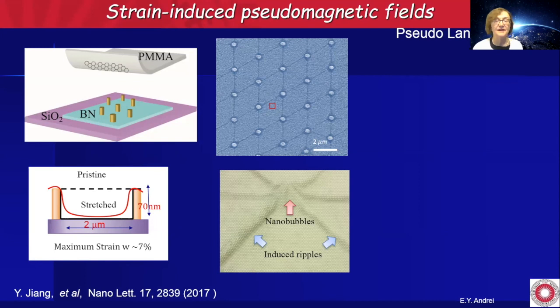This is our scanning electron microscope image of this sample. So this is graphene on top of the gold pillars. The distance between pillars is about 2 microns. And you see that, of course, because you have these pillars, just because of the topology, and you're trying to project in 2 dimensions, you must create folds that connect all these pillars. And you see this beautiful network of folds that connect them.